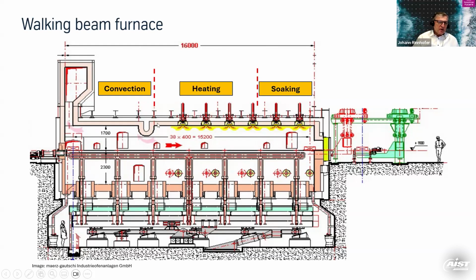And this is followed by a convection zone, which is sort of separated here with this little nose on the top of the furnace. So we use the hot gases which are going to the left side here through the furnace into the flue gas duct. And we try to get as much energy as possible from the flue gases into the steel in that area. We have no burners here at all because it doesn't make sense to have any heating here, because all the heat will go directly into the flue, and this is what we don't need. So we would increase the temperature of the flue gas, which is not a good idea in the end.